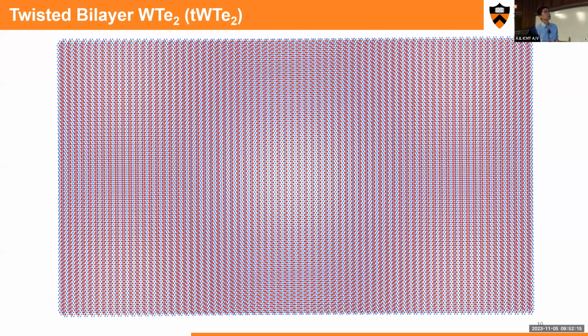Experimentally, we can actually visualize it. For example, we can do conductive AFM. We image the Moiré, and this is a real image of the Moiré superlattice. You can see the interchanging stripes, with the local conductance alternating between high and low. The distance also overlaps very well with the calculation.